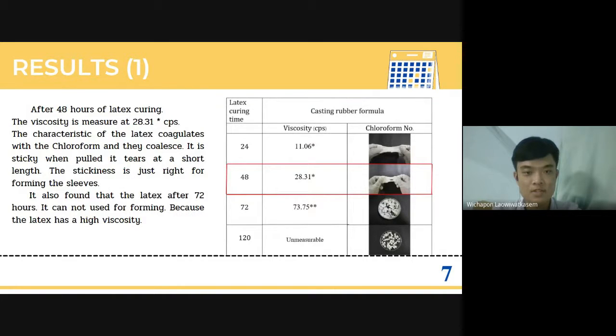Next, I'm going to talk about results part 1. Curing latex compound for 48 hours gives suitable latex. After 48 hours of latex curing, the viscosity is measured at 28.31 centipoise. The stickiness is just right for forming the sleeve. It's also found that latex after 72 hours cannot be used for forming because the latex has a high viscosity.